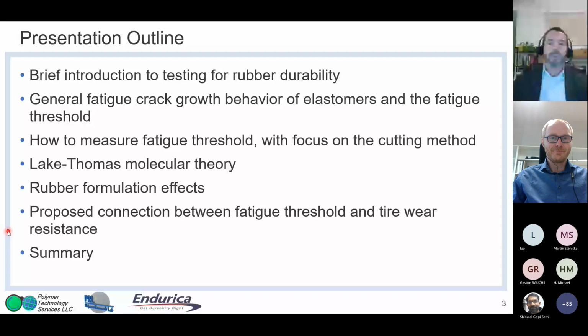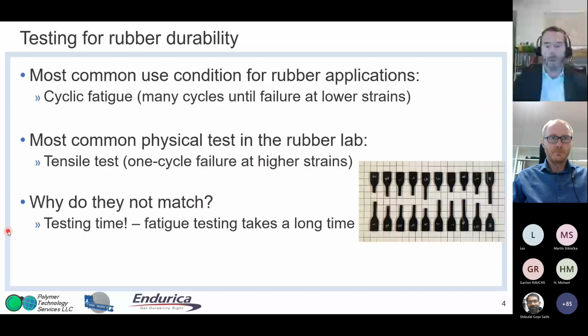So the most common way we use rubber is cyclic fatigue, at some lower strain than ultimate failure, with many cycles until failure. However, the most common physical test you'll see in any rubber lab is the tensile test, where you just monotonically pull, one cycle, until the specimen breaks. Why is there a mismatch between how we mostly test rubber and how rubber is used? Well, that's because fatigue testing takes a long time. At the end of my presentation today, you'll see that within a 1 or 2 hour testing methodology, we can get insights into the very long-time fatigue performance of materials.